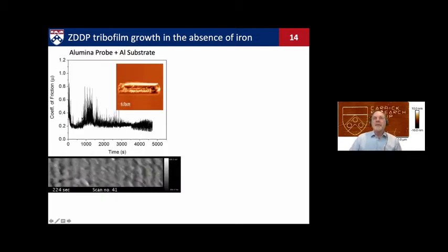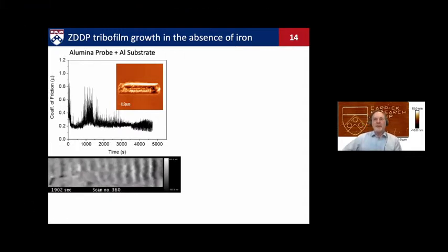So to investigate this, we looked at both aluminum and aluminum oxide, in other words, sapphire surfaces. So this is the friction coefficient versus time. And here's the time and the number of scans. And these are the topographic images of the tribofilm as it's growing. And what we see initially is a fluctuating tribofilm that eventually stabilizes. And I hope you can see these bumps here. There's quite a bit of variation in friction that we're still working to fully understand.